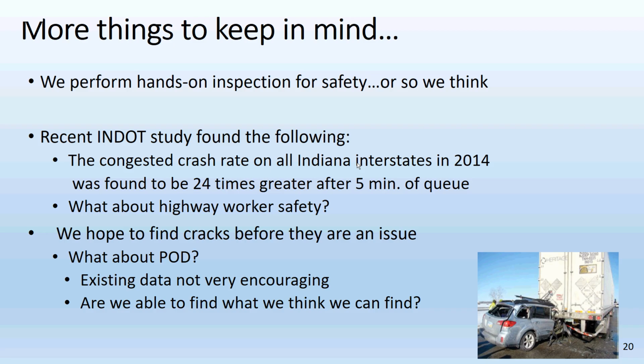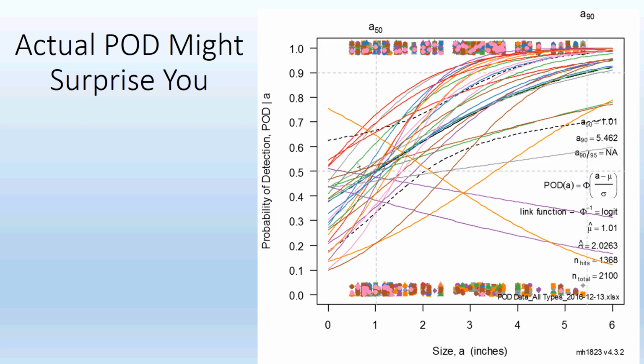This is what we found, and so I'll give you a second to digest this, but it is probability of detecting on the vertical axis, the visible crack on the horizontal axis. And so, as you imagine, generally, as the crack gets more visible or longer, we're more likely to find it. But look at the statistics there on the right-hand side, the A50 crack, the 50-50 crack, right? 50% of the time we would find or miss, it's about an inch. To get up to about a 90% probability of detection, we need about a 5.5-inch crack. That's a healthy crack, and I want you to keep that number in mind.